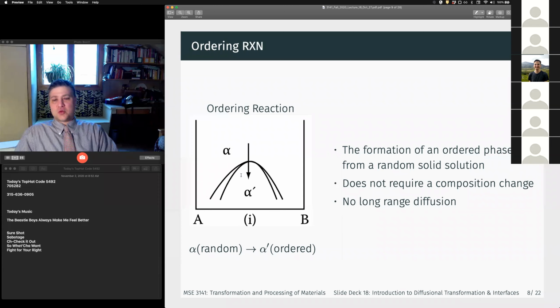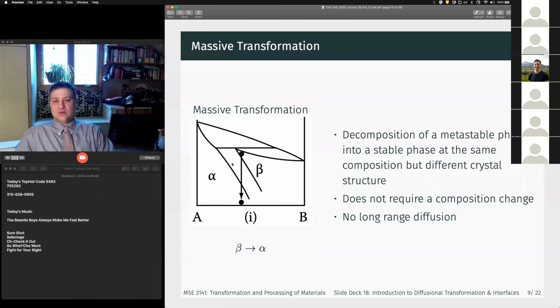All we're doing is swapping sites, atoms locally on their lattice sites to bring about an ordered structure, right? And then we have massive transformations, which is where we transform from, in this case, beta to alpha at the same composition, right? So we have a change in crystal structure in this case, but not a composition change, right? So this also doesn't require long-range diffusion.